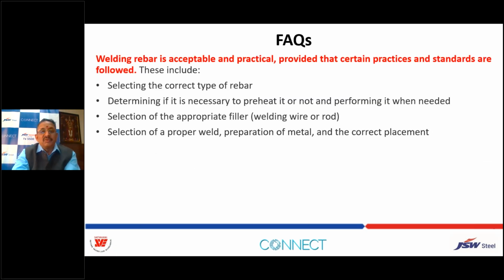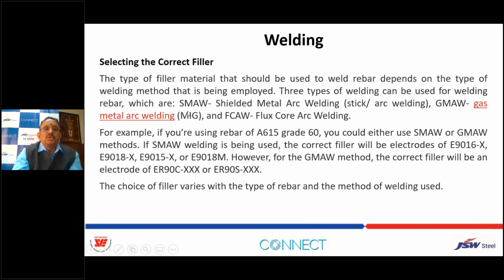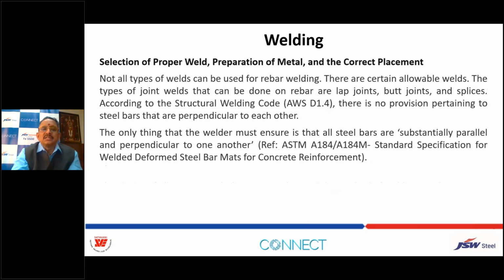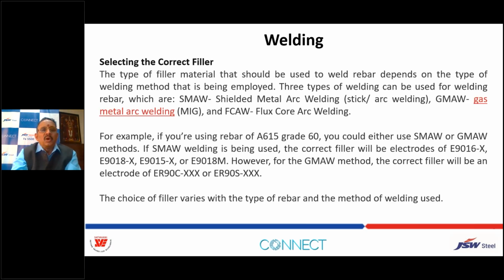And also heating is very important. When we weld, we have to do the preheating sometimes. And so we have to use this special welding, shielded metal arc welding, or gas metal arc welding, and all these methods we have to adopt. And be very careful, please don't allow welding without referring to the proper technical specification and quality tests on the weld, because our whole bond development or the stress transfer depends on this weld. So we have to be very careful while allowing welding. That's why I have given all this information on the welding actually.